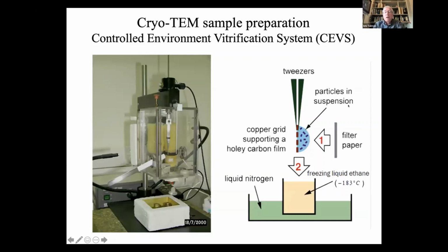Another problem that we have in preparing our specimen is that we want to make sure that the specimen is prepared at conditions that preserve it before it forms the vitreous ice. So we have to prepare it in some kind of a controlled environment. This is a homemade device that we still use. In this box, we control the humidity in such a way that we don't lose any volatiles from the specimen during preparation. Also, we can control the temperature in this box. So if we, for instance, want to make sure that the specimen is at body temperature, we can control the temperature in this box to be 37 degrees centigrade.